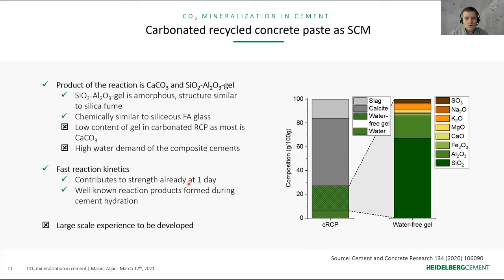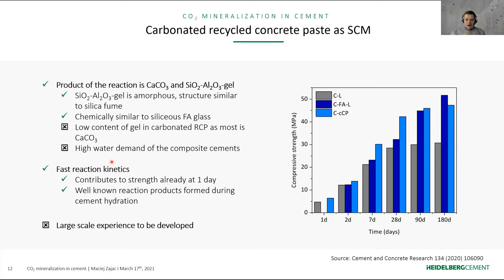One more disadvantage, of course, is the high surface area, like in the case of calcined clay, for example, which will result in a high water demand in the composite cements. We are currently working on those challenges. Okay, as I told you, the gel contains pozzolan. It is very reactive, and we can see the results of this pozzolanic reaction in terms of the evolution of the compressive strength of the composite cements.